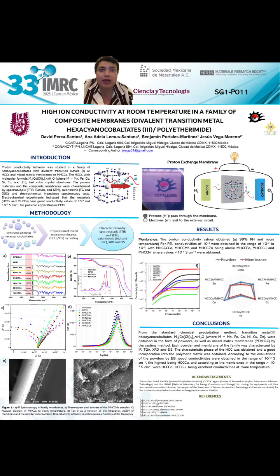For the results obtained in the membranes, the proton conductivity values obtained at 99% relative humidity and room temperature were in the range of 10^-2 to 10^-3 Siemens per centimeter, with the hexacyanocobaltates of cobalt, manganese, and zinc being above iron, copper, and nickel, where values of 10^-4 Siemens per centimeter were obtained.